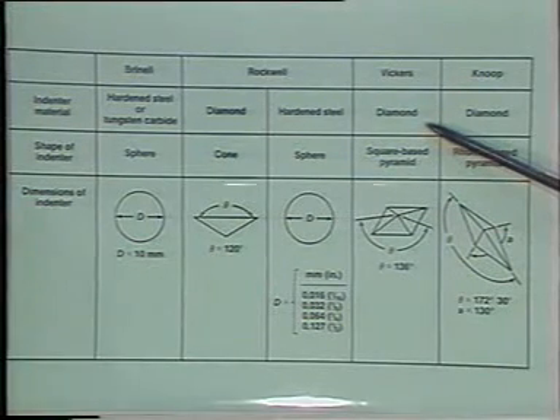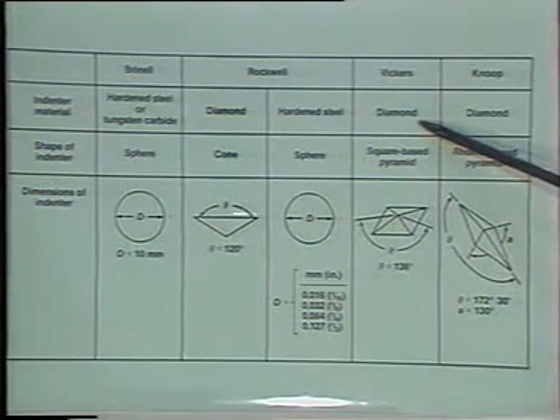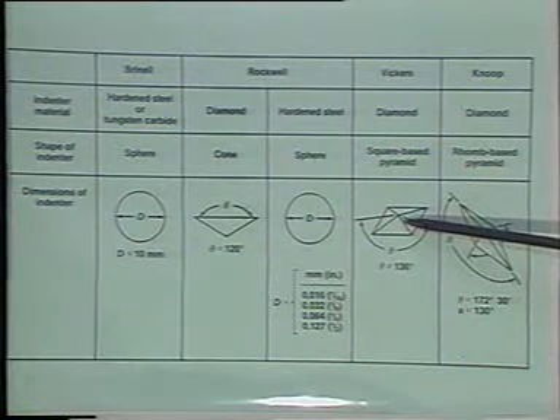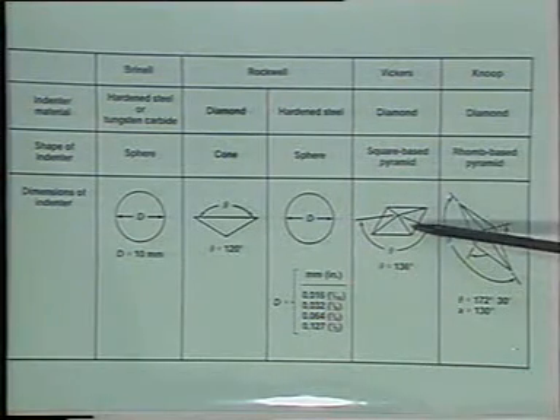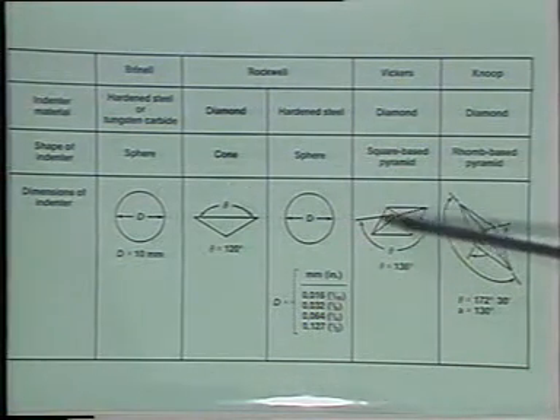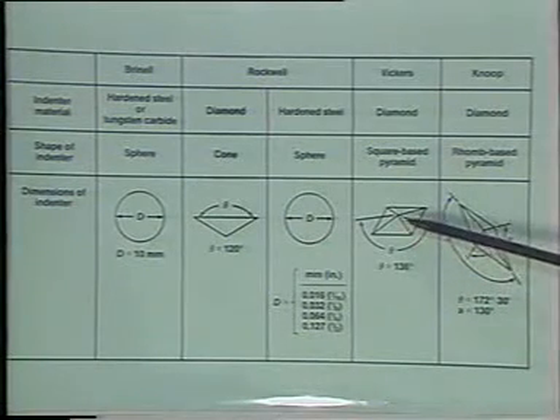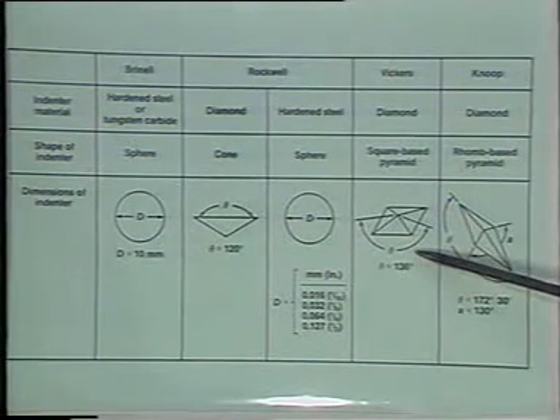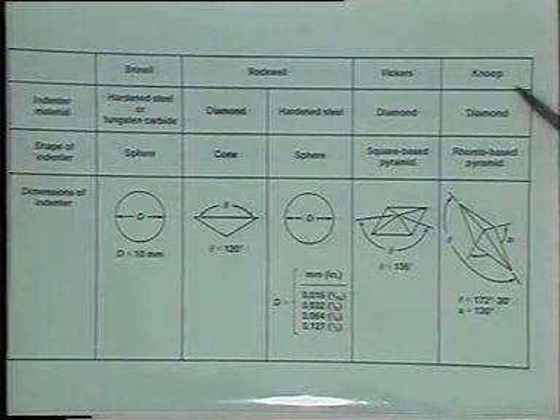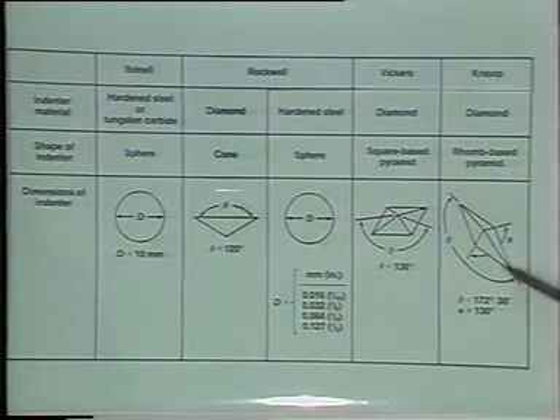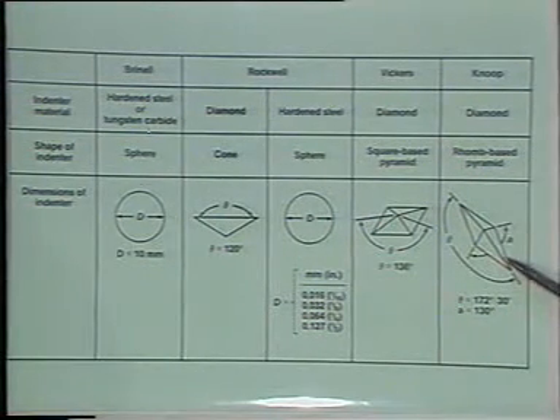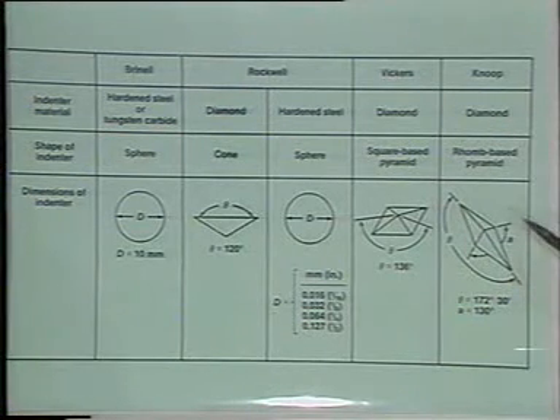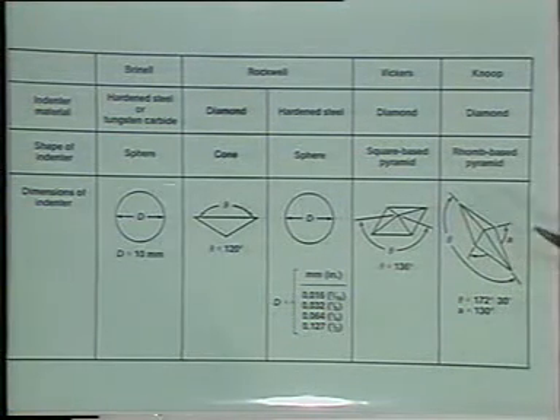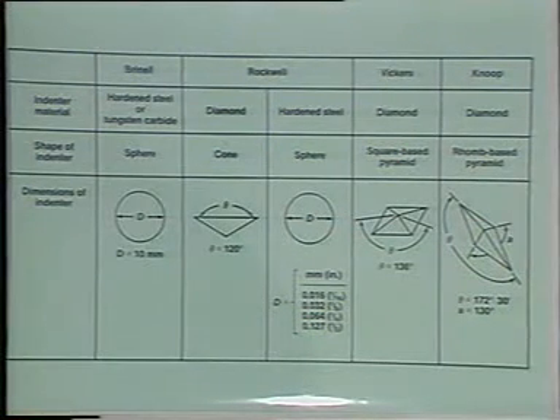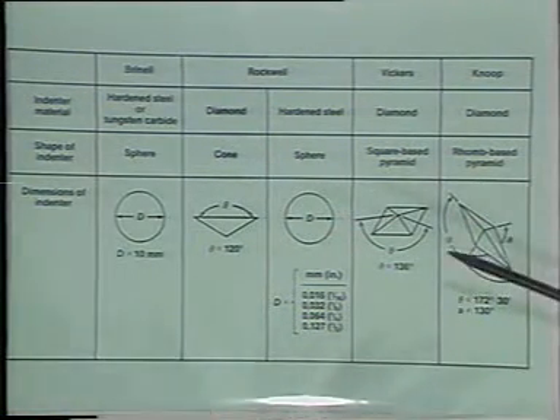The Vickers device is very similar to that. We have a penetrator, and the penetrator, in this particular case, is a pyramid, and the pyramid is pushed into the material and leaves a structure that's almost square, and we can measure the diagonals of this and get a relative hardness number. The Knoop is almost exactly the same, except the diamond in this case is engraved or carved to look like a rhomb, and we get a rhomb-based pyramid impression that we can measure and, again, get the hardness.